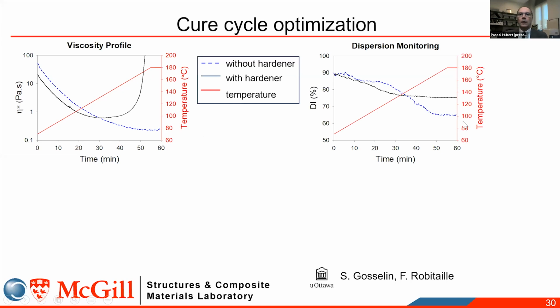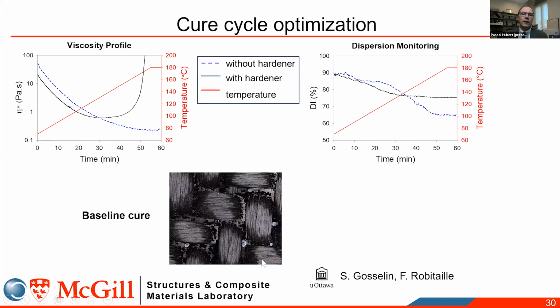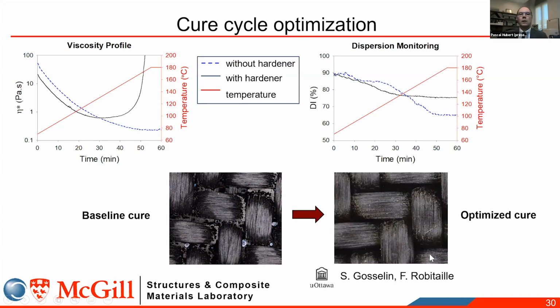a lower number. And once we have that tool, then we can do all kinds of analysis with different heating rates, different nanotube ratios, and so on. We can start with maybe a process that leads to a lot of aggregated nanotubes, as you can see here in this image, and through some optimization, we can then obtain a much more stable dispersion of the nanophase. So these two examples just illustrate how, with the tools that we have today, the micro-CT, being able to visualize the process using specialized fixtures to monitor all the key process parameters during cure can give us better insight, a better understanding of the processing science, and therefore reduce the risk in our manufacturing.